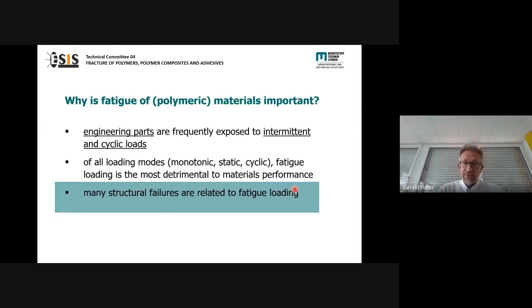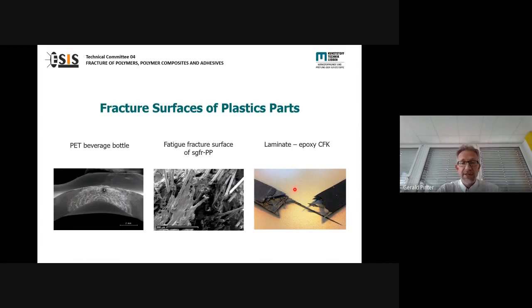As already mentioned, we see a lot of failure in polymers and in fiber reinforced polymers as a result of fatigue load. Here is even a failure case we dealt with in the last years, where we looked at a PET beverage bottle, where fatigue failure was a result of different overnight temperatures in the storage rooms. Here you can see a typical fatigue fracture surface of a short fiber reinforced polypropylene, and here a carbon fiber reinforced composite laminate, a typical specimen failing under fatigue. So that is a kind of introduction.